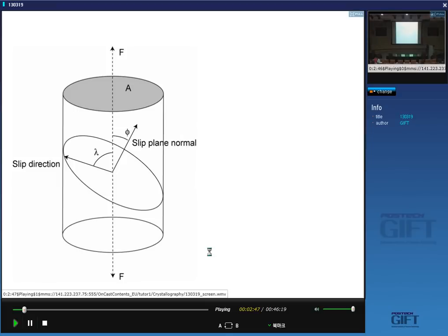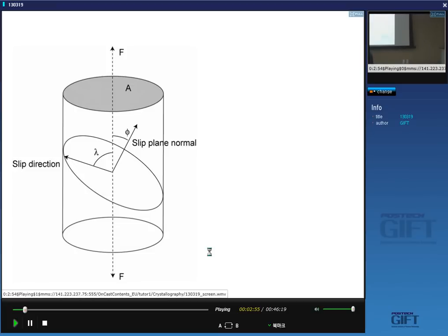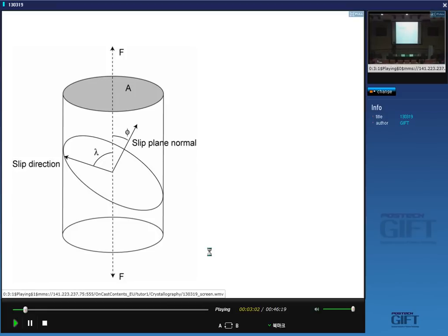Let's think about the deformation of a single crystal. Since it's a crystal, it will have anisotropic properties, so there will be particular planes on which slip happens more easily than on others, and particular directions on which slip happens more easily. A slip plane is usually the most densely packed plane in the crystal. The reason is that if you've got spheres touching each other, the next layer doesn't sink into the underlying layer, so it can glide easily. Whereas if there's a lot of space between atoms, the layer on top sinks in and it's quite difficult to slip. So generally, slip planes will be close-packed planes.